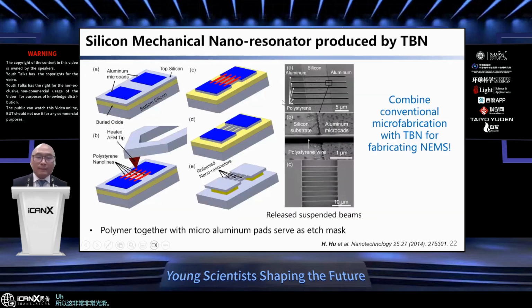More importantly, I developed a method that can combine conventional microfabrication with this TBN method for fabrication of NEMS devices, or nano electromechanical system devices. So this is by using conventional UV lithography. So we make microscale aluminum micropads. So the AFM probe can deposit polymer nanowires connecting these micropads. So the micropads, together with the nanoscale polymer nanowires, serve together as an etch mask.